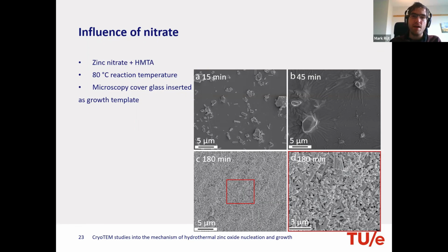And we found that instead of forming something like layer basic nitrate, we actually formed wülfingite zinc hydroxide at the beginning, which grew on present surfaces and then likely promotes the further formation of an evolution to zinc oxide on those surfaces later in the process.